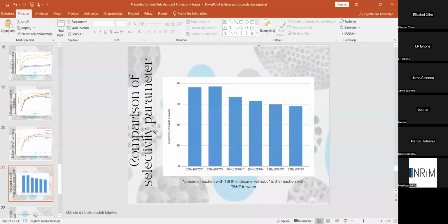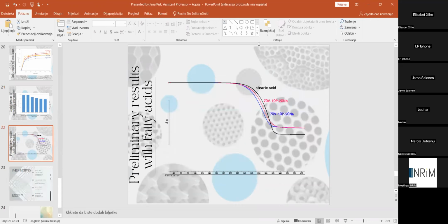And also what we can see, the selectivity with TBHP in decane or TBHP in water is more or less the same. Which is quite good, again, and supporting the principle of green chemistry and what we can follow with the green chemistry. At the end, what we try to do with those samples of glasses and glass ceramics, and in fact, it is the fatty acid oxidation.